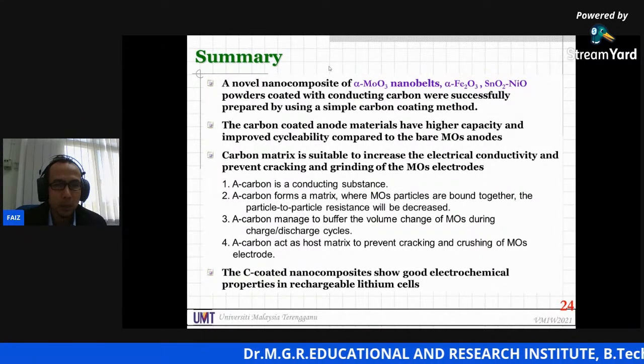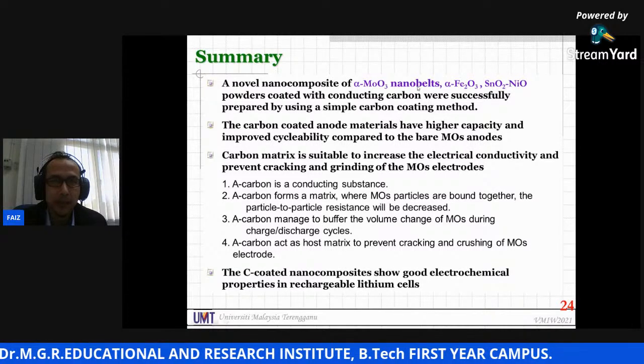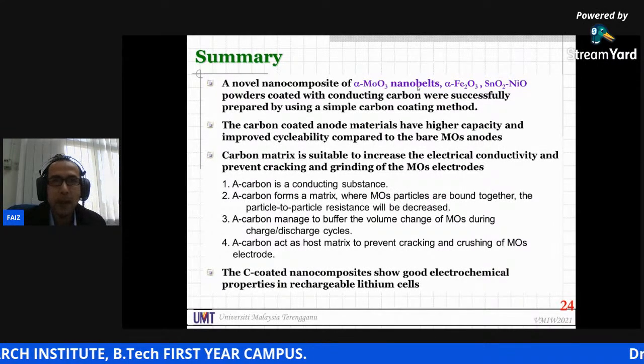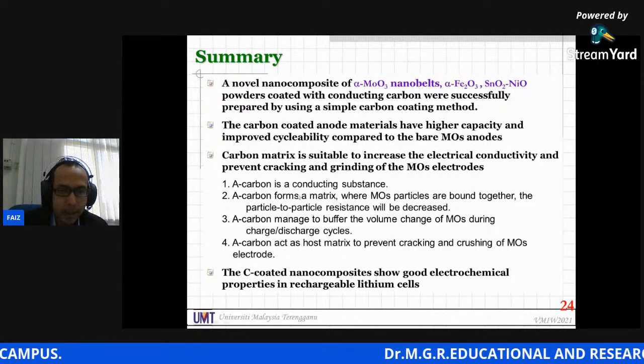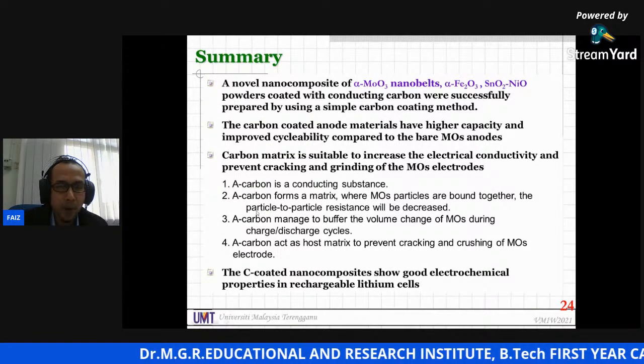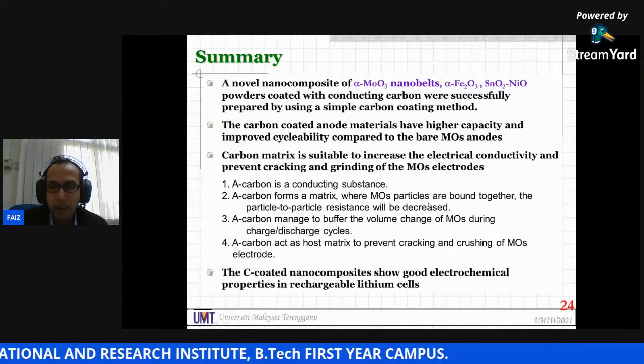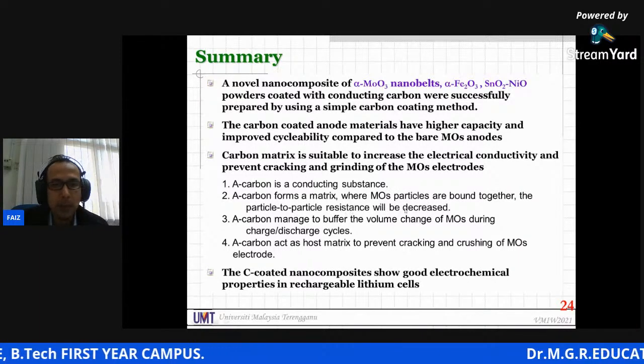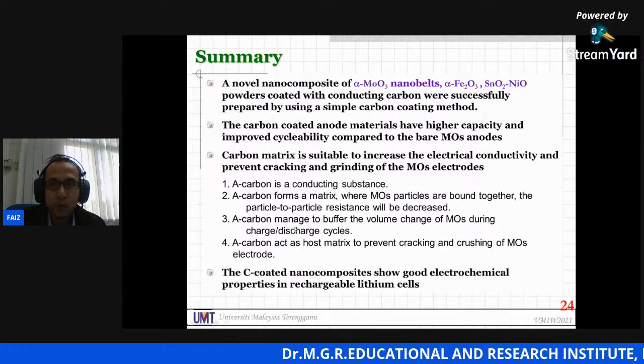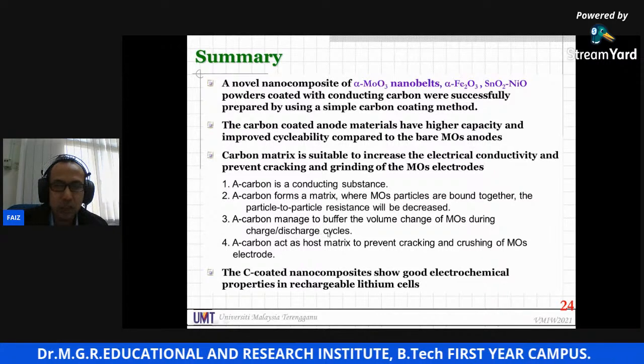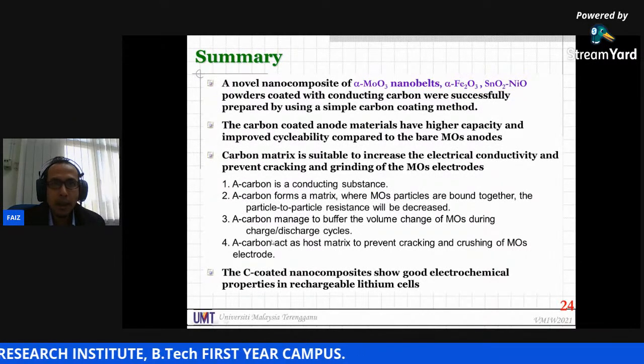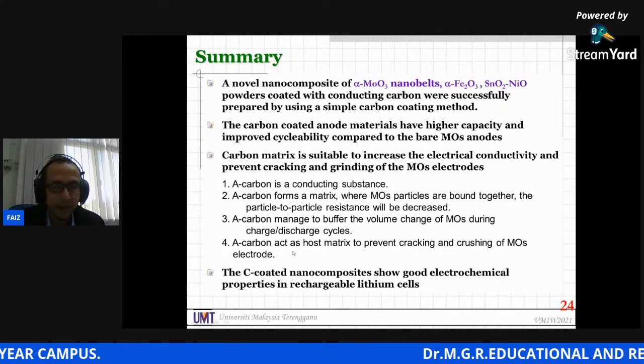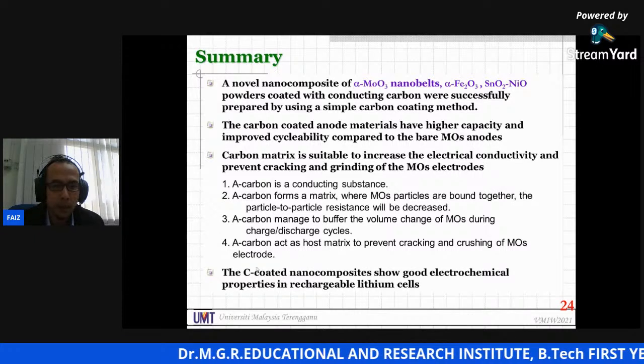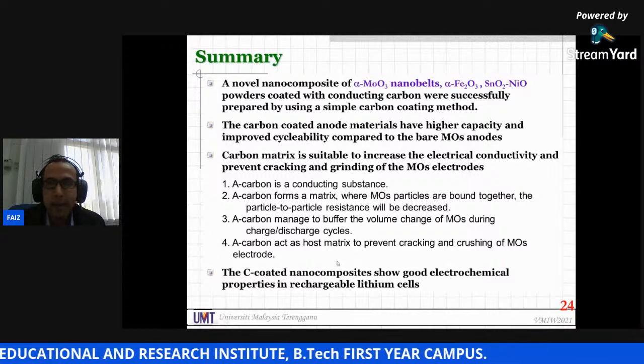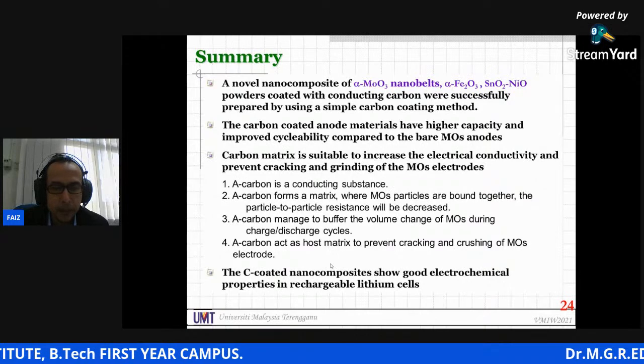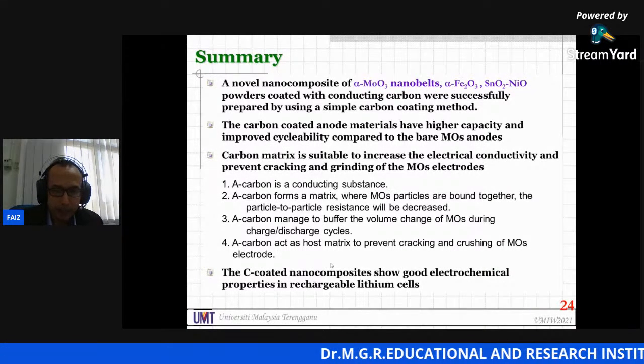Next, the carbon matrix is suitable to increase the electrical conductivity and prevent cracking and crushing of the metal oxide electrodes. In general, carbon is well known as a conducting substance, and in the matrix form of carbon, you can see that the metal oxide particles can be bound together. The particle-to-particle resistance will be decreased. This carbon also managed to buffer the volume change of the metal oxide during the charge-discharge cycle. And next, this carbon can also act as a host matrix to prevent cracking and crushing of metal oxide electrodes. As a result, the carbon-coated nanocomposite material provides outstanding electrochemical properties in rechargeable lithium cells as shown in previous slides.